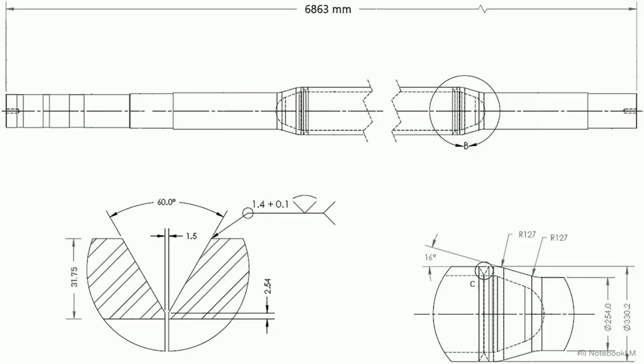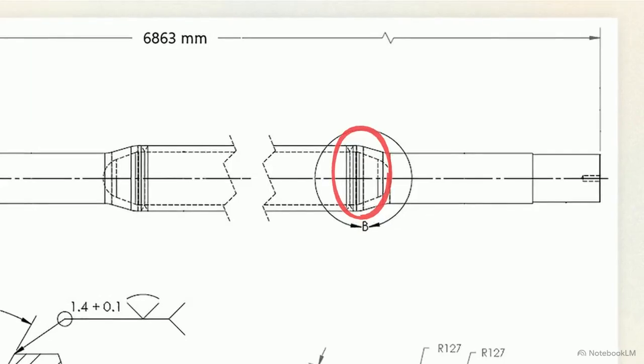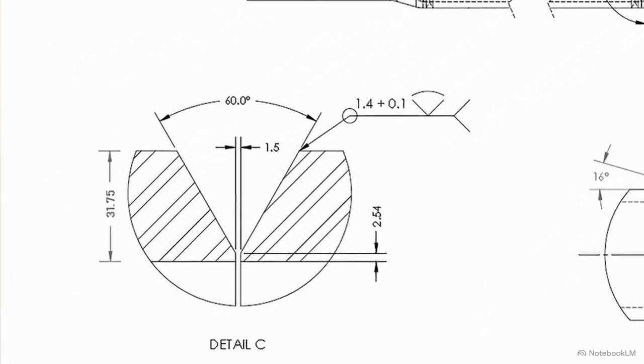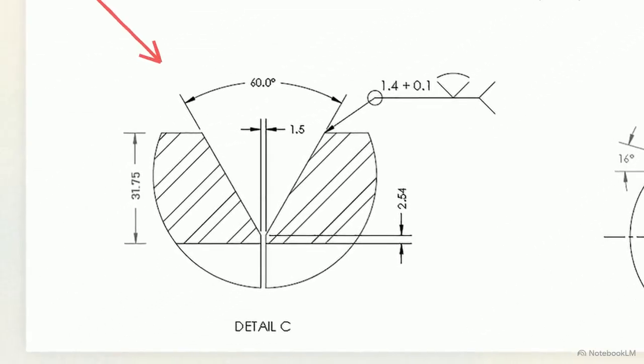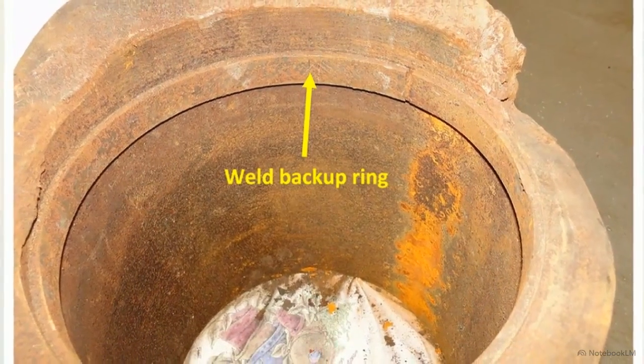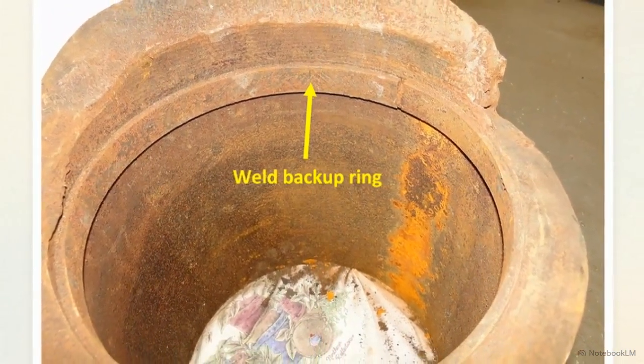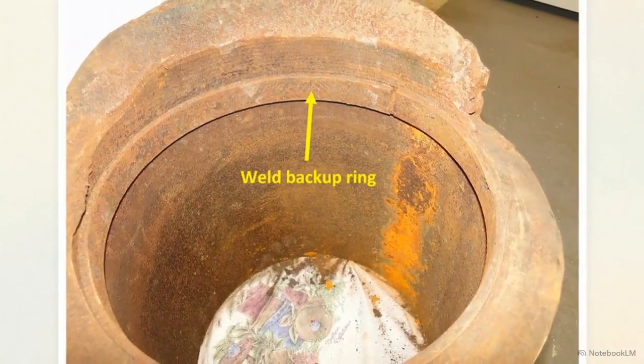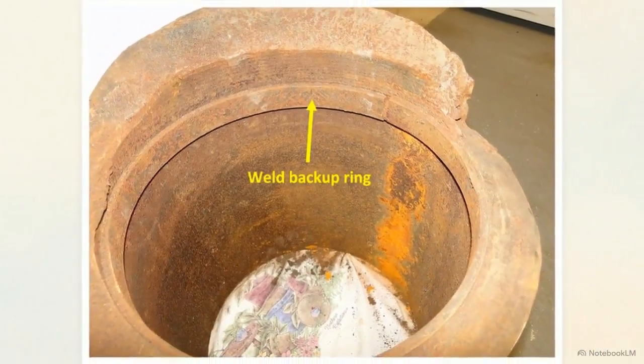This engineering drawing shows the baseline geometry of the failed shaft, focusing on the location where the hollow segment transitions into the solid terminal section. Detail C specifies how these two thick sections were fused together using a 60-degree single V weld joint. To construct this joint, engineers utilized an internal backup ring. Welded directly inside the hollow shaft, it supports the molten weld pool during fabrication.